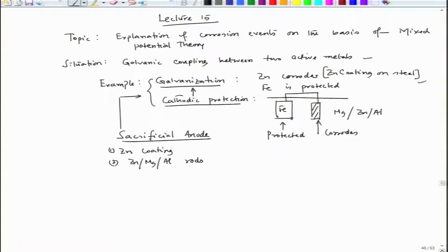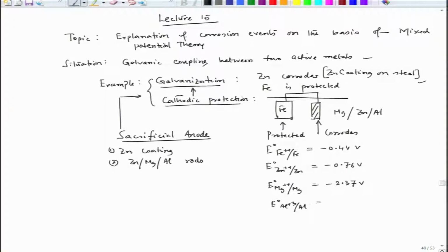if I consider their potential values. So, for example, E0 of iron equal to -0.44 volt, then E0 of zinc equal to -0.76 volt, E0 of magnesium equal to -2.37 volt, E0 of aluminium 3+ to aluminium is -1.662 volt. So we could see that iron, zinc, magnesium or aluminium, they are exposed to the environment